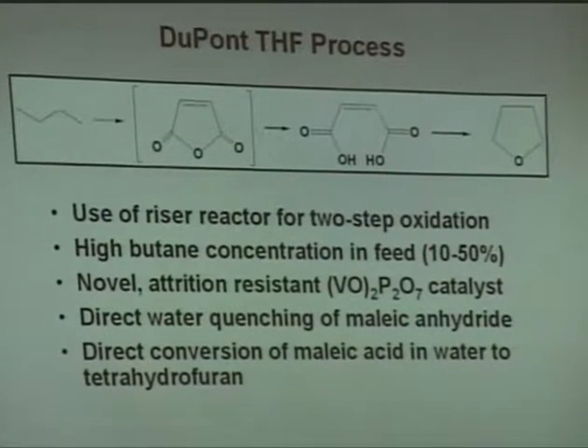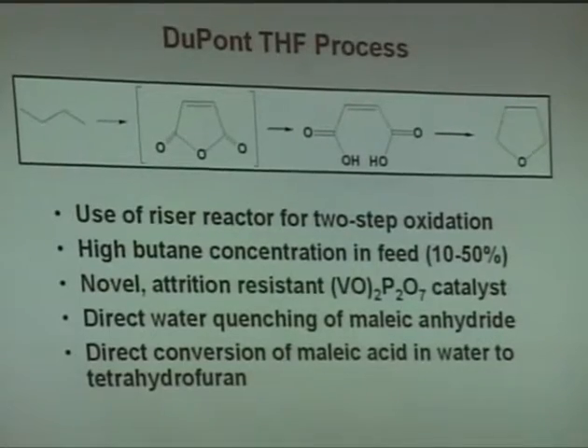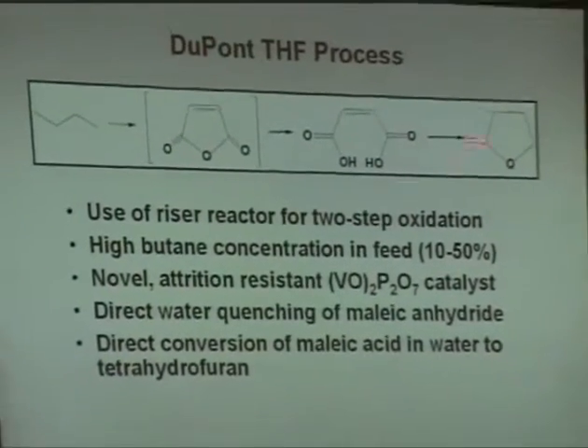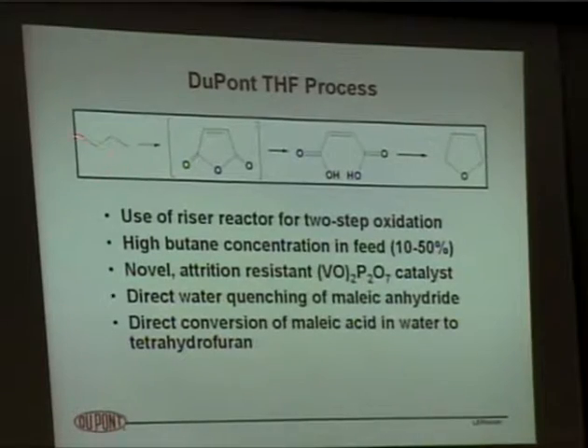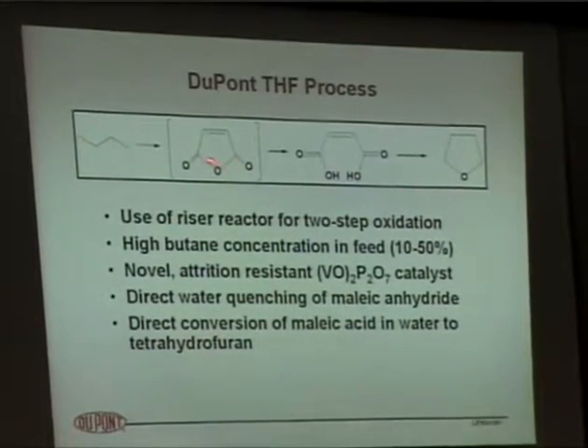Okay, the only commercial example that I know of is our process that we've worked on for a very, very long time, went commercial in 1996, involves the oxidation of butane to maleic anhydride as an intermediate. Most people purify, separate the maleic anhydride, and reduce it down to tetrahydrofuran. We actually come out of our reactor with a water quench, as aqueous maleic acid. The maleic acid is then hydrogenated directly out of that aqueous solution in a slurry bubble column reactor to make tetrahydrofuran. So this example, I'll show you some more details in a minute here.